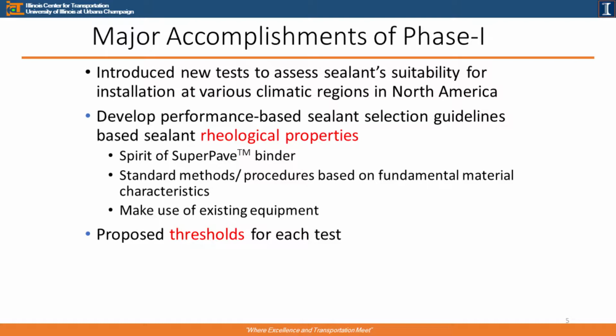As they found that the sealant material should be compatible with the asphalt binder, they utilized the concept or spirit of the superpave binder specification. And then they also utilized standard methods and procedures based on fundamental material characteristics, which is basically rheological properties. And then make sure we can utilize existing equipment, because every state DOT has problems with securing funding. If we can utilize existing equipment, that's much better than purchasing new equipment. And then also, the accomplishment of phase one was proposing a threshold for each test.